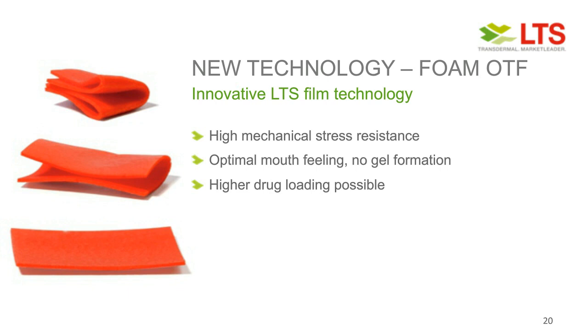As you can see also in the picture, these films have a very high mechanical stress resistance. So you can fold them, you can bend them, they're not brittle, they don't break. They provide a very optimal mouth feeling, and they don't form a gel on the tongue, like HPMC does, where you have a strange, odd feeling in the mouth, and it takes not just the 5 to 10 seconds for the film to dissolve, but also a much longer time for the gel to finally dissolve and be swallowed. So this is something we really look at to get an improved mouth feeling.